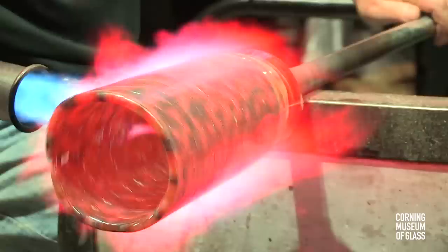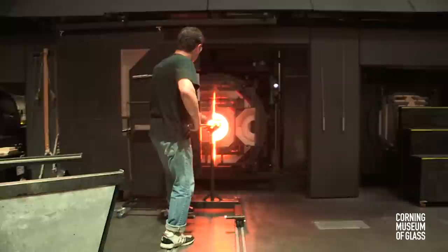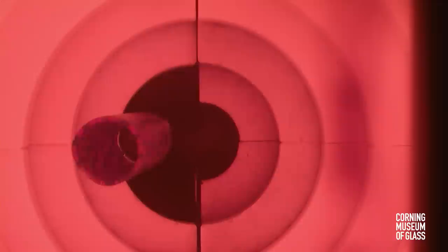Also, he's keeping in mind that the very edges get the hottest. They seem to suck up the heat, and then that heat causes the glass to coagulate and crawl back on itself. So he heats the middle and leaves the ends to get a little colder when he's outside of the furnace before he goes in for a submersive heat here called a flash.